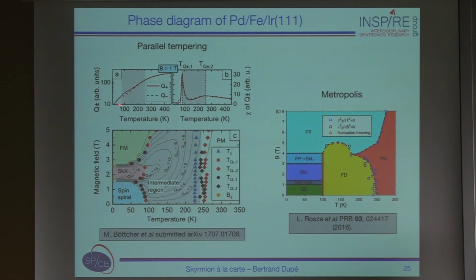And that's the first surprise here. You see that although you have DMI actually included, both Q plus and Q minus are always increasing as a function of temperature. And actually, when you go into this shaded region here, these two curves start to split, and you have a difference in the creation of Q plus and Q minus. If you look at the susceptibility, you indeed have a sharp peak here at low temperature, and you have a broad peak here at high temperature, which was also seen with Dasgupta.